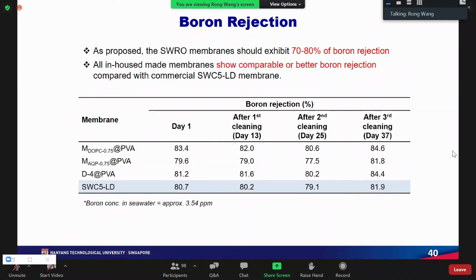We also test the boron rejection for our newly developed membranes. We know SWRO membranes need to exhibit a reasonable boron rejection, like 70 to 80%. We tested all the in-house made membranes; they show comparable or even better boron rejection compared with the commercial SWC5 LD membranes, because this is one of the best membranes on the market now.